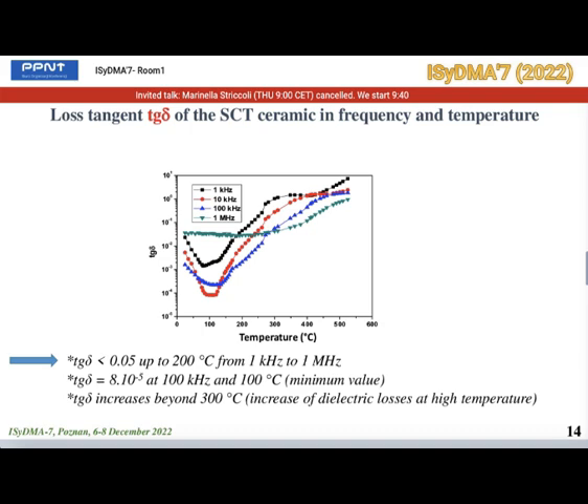Concerning the loss tangent, it remains smaller than 0.05 up to 200 degrees Celsius from 1 kilohertz to 1 megahertz. The minimum tangent value obtained for the SCT ceramic is 8 times 10 to the minus 5 at 100 kilohertz and 100 degrees. It is certain that these low loss values are very interesting for the development of high quality lead-free ceramic capacitors for applications requiring high temperatures. Beyond 300 degrees Celsius, the loss tangent increases sharply. This may be due to the increase of dielectric losses at high temperature in the material.